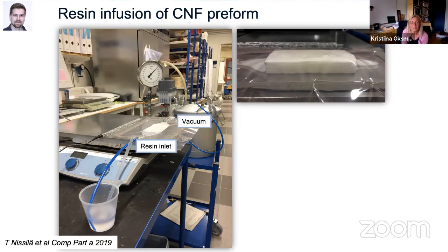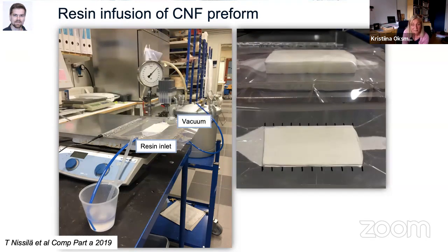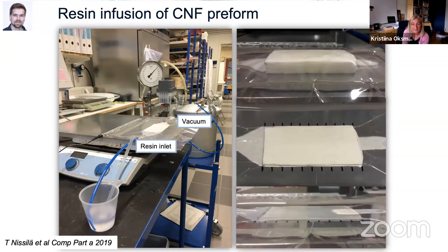We have the preform here before resin is applied. Then after the resin is applied, of course, we are compacting the preform, and then here we are infusing it, and it's going very well. The fiber content is only 12%. And of course, we are trying to work to increase that fiber content. Here is how the composite looks.